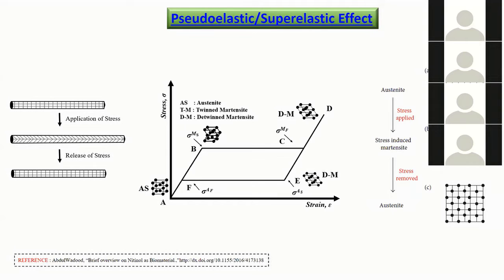achieving this kind of phase transformation and the associated recoverable strain simply with the addition or removal of stress itself, okay, stress or loading. And the temperature in any case is constant. It's isothermal. So what we are seeing here is that it is initially in the austenite condition. And if we apply stress to it, it converts to martensite and detwinned martensite, as you can see here. So it stretches up to a certain level.